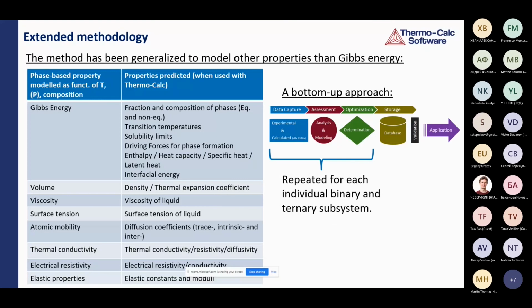It's also an extended methodology. We have used this method to also predict other properties than Gibbs energy. We use the same kind of methodology to also simulate volume, viscosity, surface tension, atomic mobility, thermal conductivity, electrical resistivity, and elastic properties. And the CALPHAD methodology is a bottom-up approach, and with that we mean that you do it for pure elements, binary systems, and ternary subsystems, and then you extrapolate up to multi-component systems, you do validation against commercial data, and then you can use it for real engineering applications.